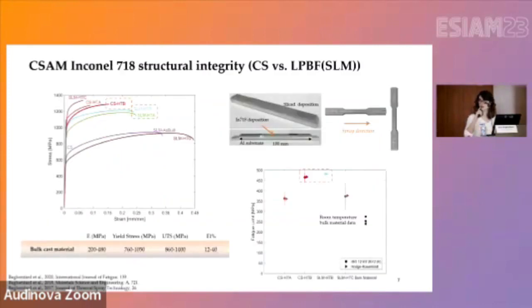So I would start with the first topic, which is about the structural integrity of additive manufactured parts that are made by cold spray. We have done some research in this area, getting some thick coatings and then separating the classic dog bones from the deposits. We have performed tensile tests on the cold spray additive manufactured samples and compared them with laser powder bed fusion or SLM samples made from the same powder. After the proper heat treatment, you can see the results for static tests are comparable between SLM and cold spray.